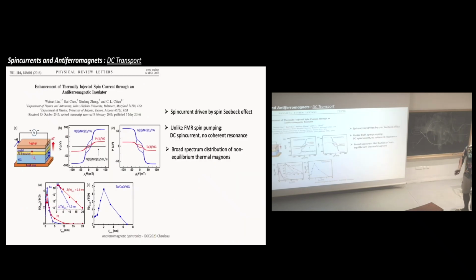Okay, next. So now we're coming back a bit to your point, because in all the previous studies they excited the spin current with ferromagnetic resonance. So you have a spin generator, which is a ferromagnet. You drive it at the ferromagnetic resonance. It's a spin current, which is very far from the antiferromagnetic resonance. Then you have a spin current. But you have another way of having a spin current.